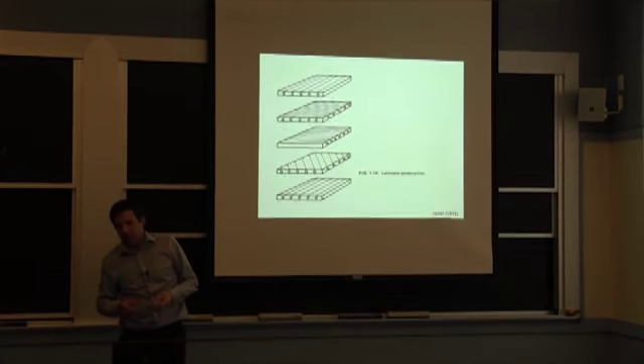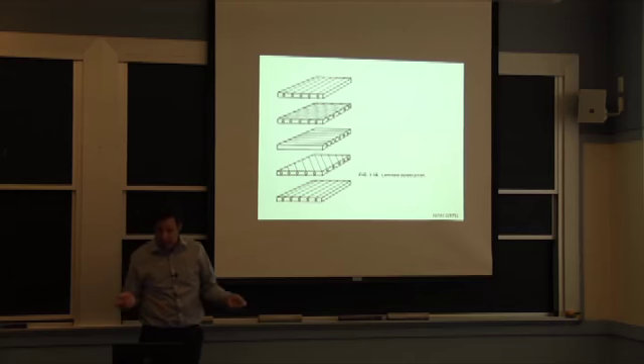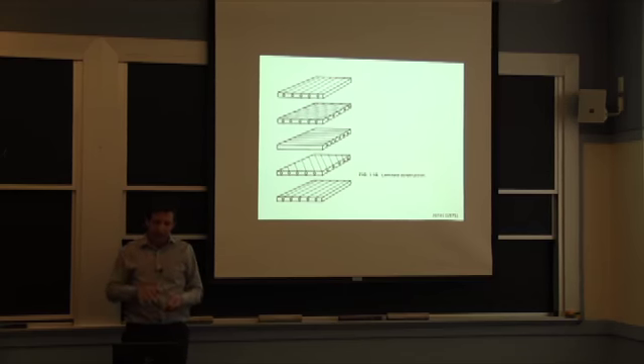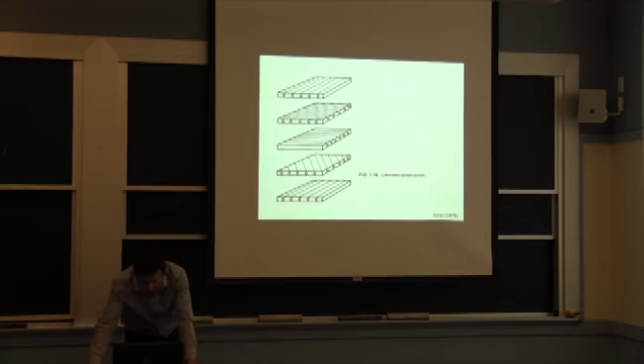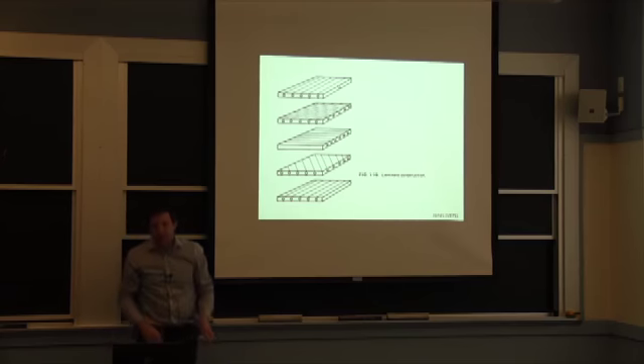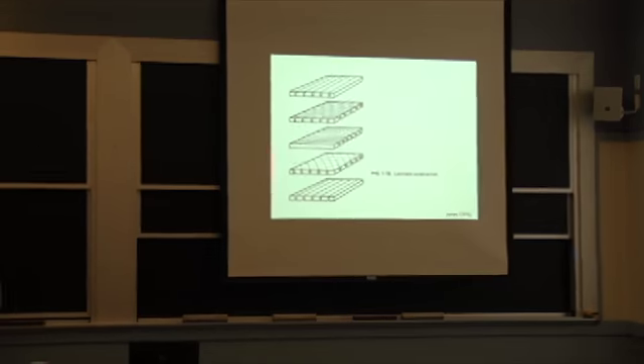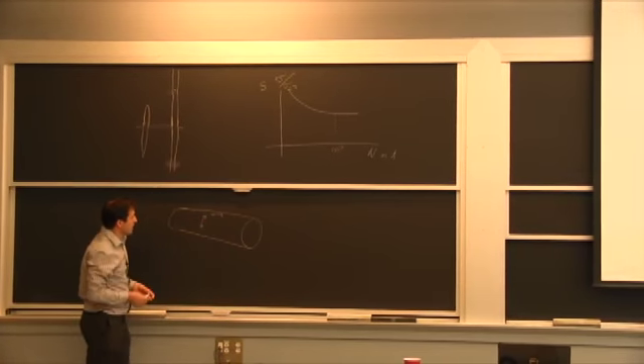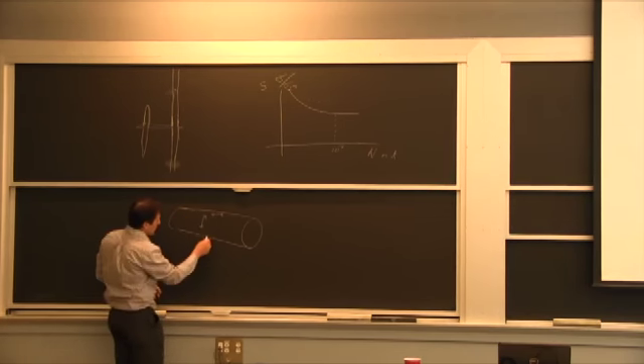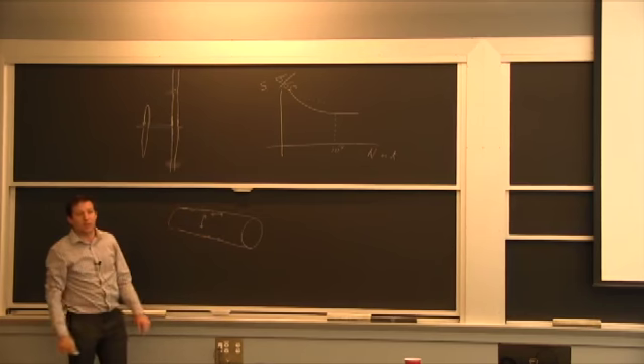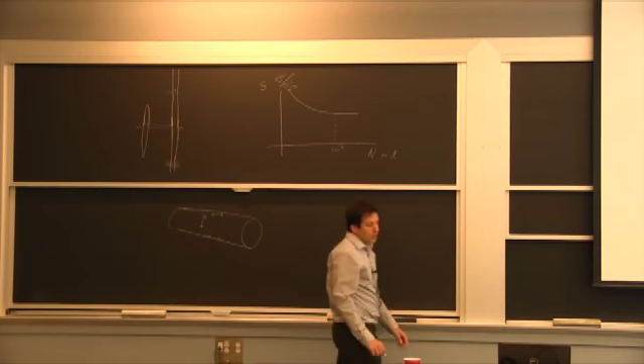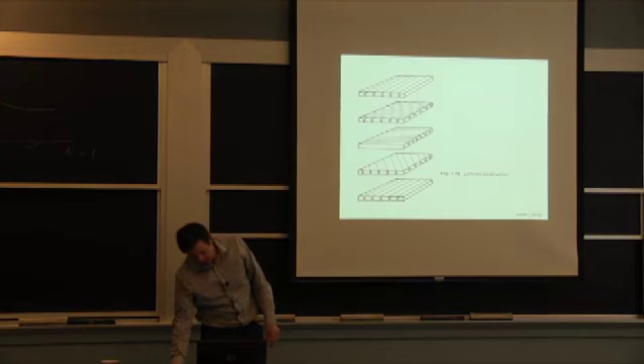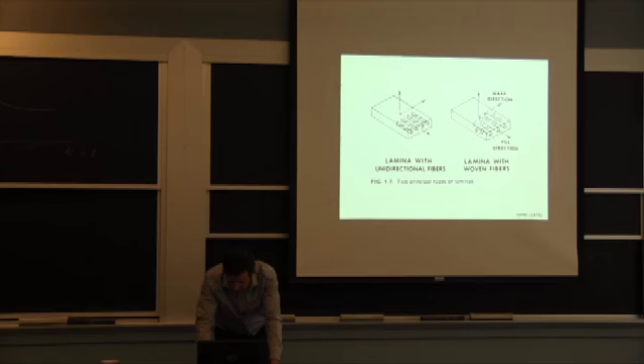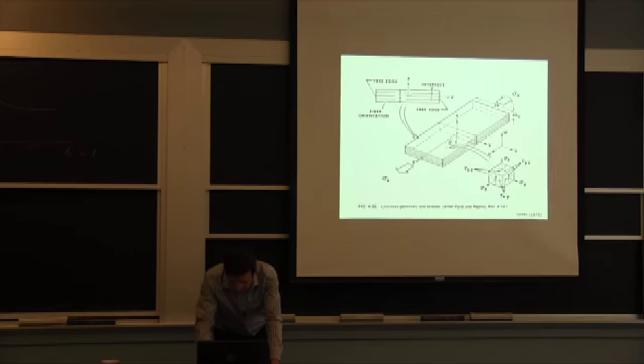There's always a risk, mostly from an analysis standpoint, but also from a behavior standpoint, when you stack different layers with different orientations. So this one here would essentially still be, well, maybe a little stronger in this direction here, especially if you have bending loads. So you have to determine, for one condition, this one, the longitudinal tension is likely to be through the thickness unless you're in the buckling. So if you're looking into the compression here, you can have some bending load as well. So you have to make a decision, which layer are you going to try to optimize for the skin? And you can't do it any way you want. I'll explain that right here.